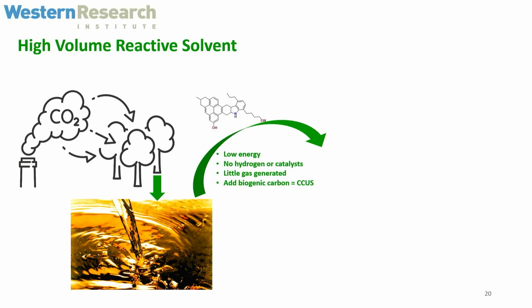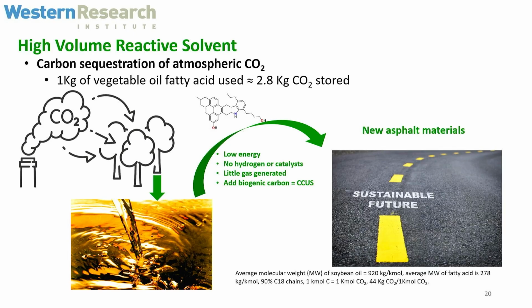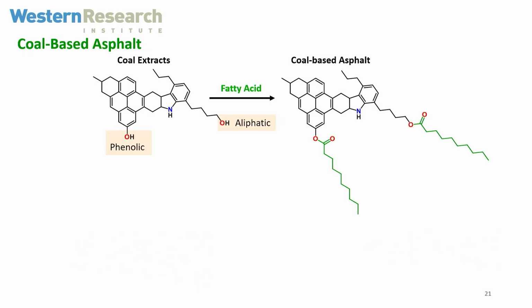And then we actually add some biogenic carbon into our product, which has some additional benefits, especially if we're looking into the future. So if we take a kilogram of vegetable oil fatty acid and we use that in a product, you're going to store basically for each kilogram 2.8 kilograms of atmospheric CO2. So we kind of like this concept of marrying fossil fuels with something from the bio side of things. And so we did these reactions, and we do end up getting a material that is now this nice, beautiful viscoelastic substance. It's quite sticky, so it looks like it has the physical properties that we want.